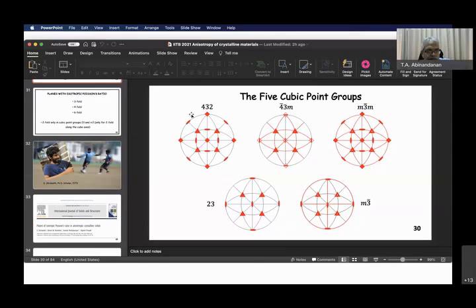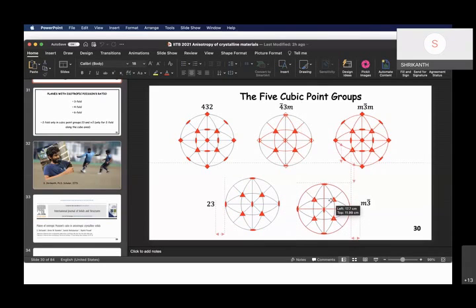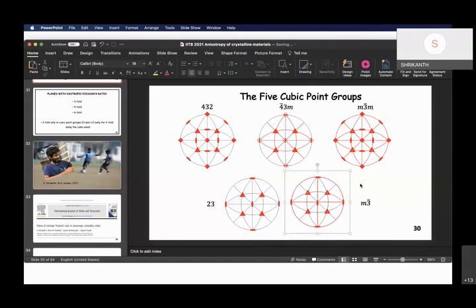Some directions will be dependent on the compliances. Like the zinc case that sir showed, it's an angle at 56 degrees. If I take another HCP metal, it might be some other angle, so there it's a compliance-dependent direction. But the common fact is that the 001 or the six-fold axis is going to be isotropic irrespective of the compliances. That's correct. Whereas the other one at 56 degrees that you mentioned, how do you look for that direction though?